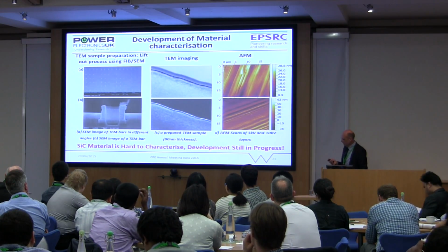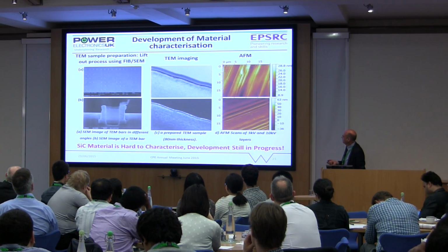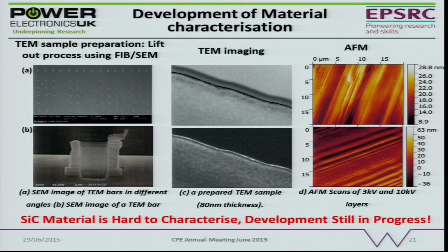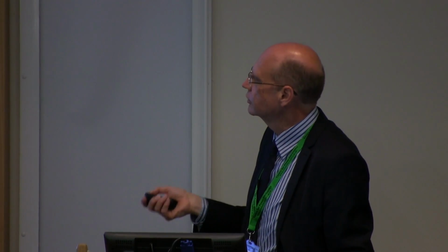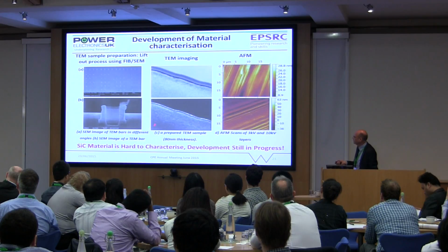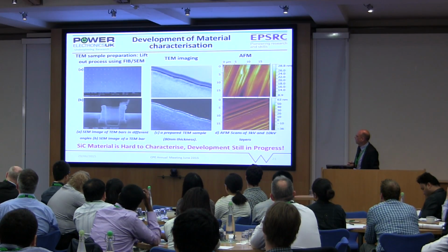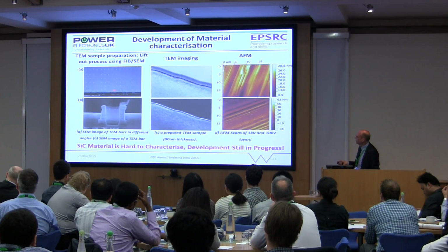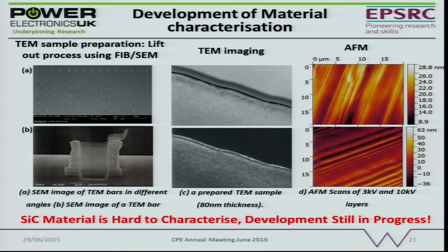And some of the physical characterization that we've done on those layers is shown here. Using transmission electron microscopy, what you have to do with TEM is to cut out very thin films through the structure that you want to look at, so that you can pass electron beams through it and look at the cross section. So we've developed a novel technique for making very thin sections using standard lithography to start with. It improves the speed at which you can do that dramatically. There's some pictures of some of the